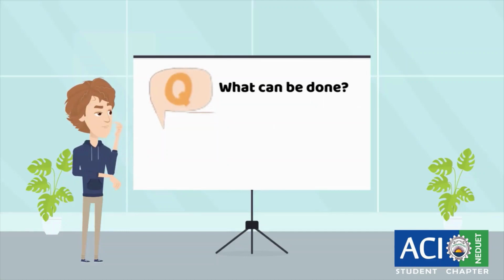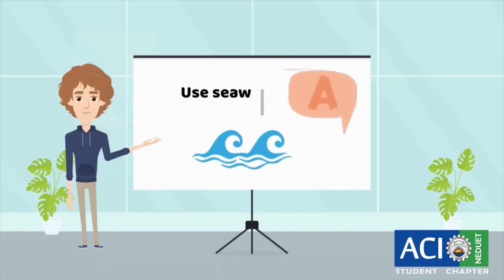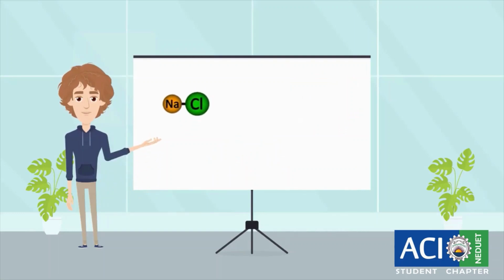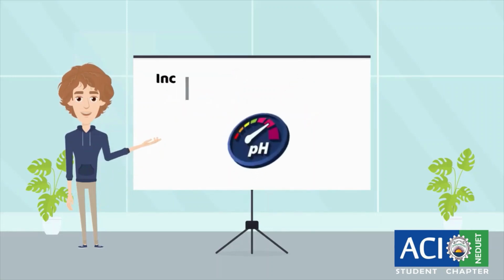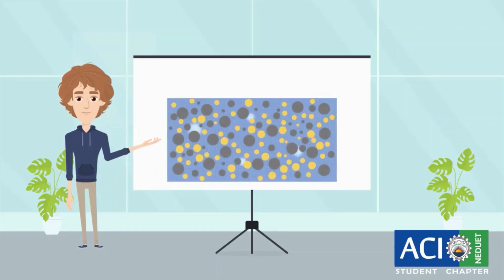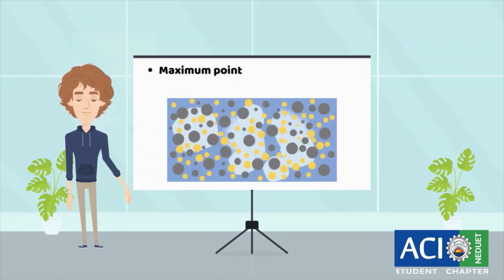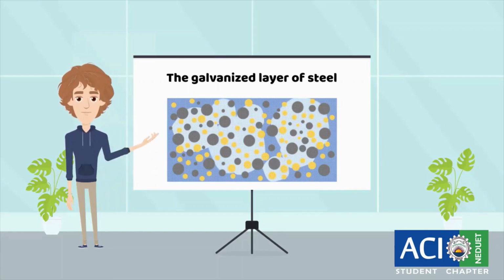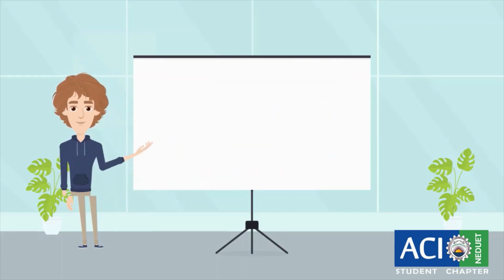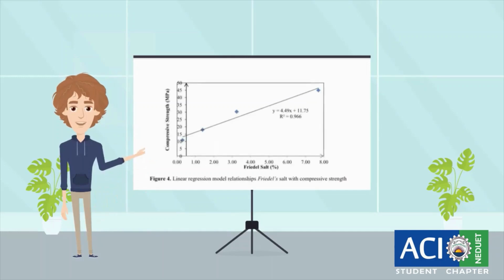But what can be done to eliminate calcium hydroxide from concrete? The answer is simple: using seawater. Abundant sodium chloride present in seawater reacts with calcium hydroxide to form calcium chloride. Calcium chloride then reacts with tricalcium aluminate to form Friedel's salt, which increases the pH and activates hydration of the cement, providing a denser paste structure with smaller pores. If the chloride ions contained in water react with cement, some of the cement hydration products will bind chloride ions in the concrete either through chemical bonding or through physical adsorption. When the amount of bound chloride has reached its maximum point and there are no more elements or compounds in cement that can bind chloride, the remaining ions penetrate into the galvanized layer of steel. Therefore, it can be concluded that the presence of NaCl in the seawater can bind calcium hydroxide compounds, causing the compressive strength of concrete to increase substantially.